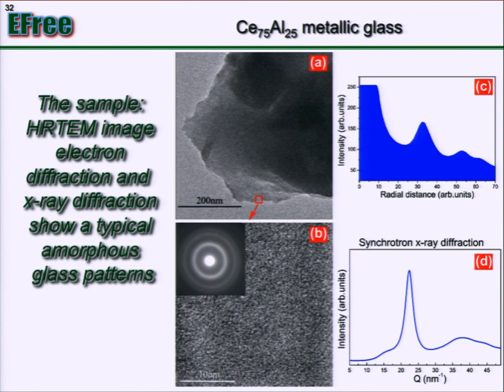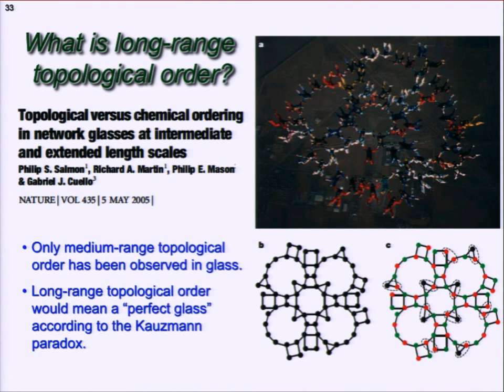And maybe the glass originally has nanocrystals in there, so we did high resolution TEM and looked at the X-ray diffraction and the electron diffraction, and in all of this, you really don't see any crystal in there. So there's no way this has nanocrystals. It did not start with nanocrystals and just grow. So the final conclusion is that it is a long-range topological order. It's not a long-range spatial order.